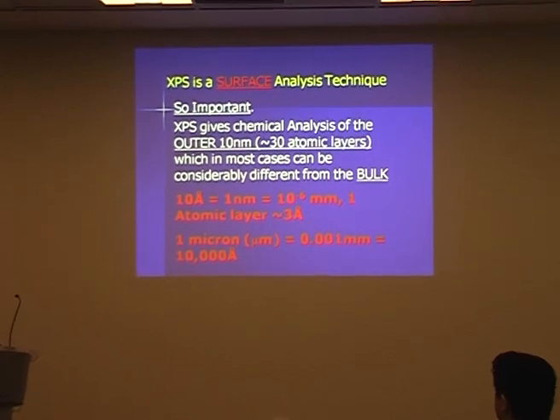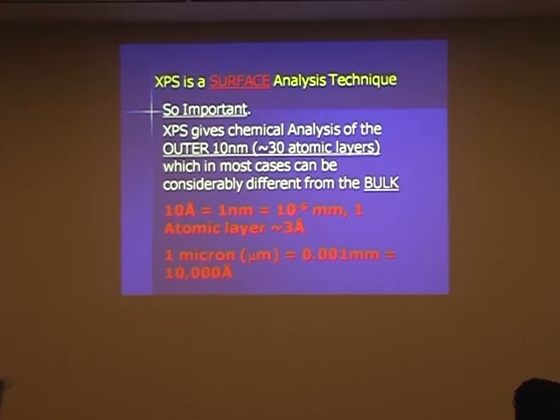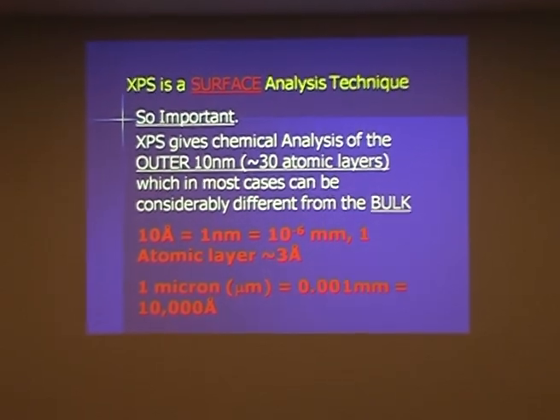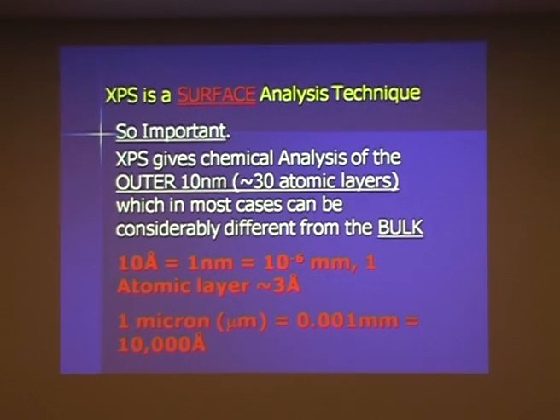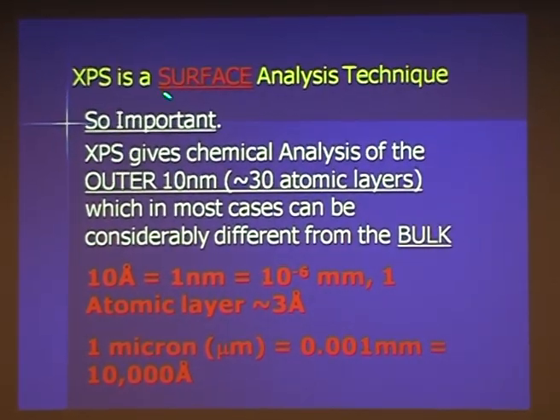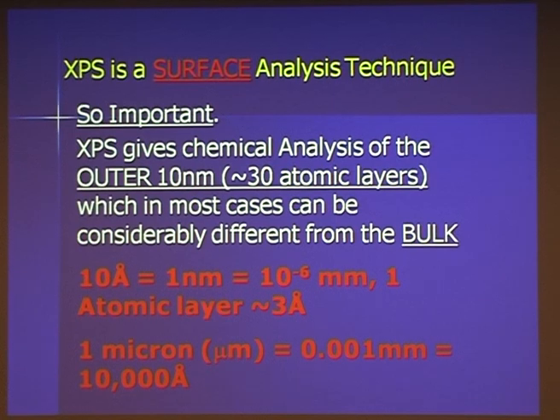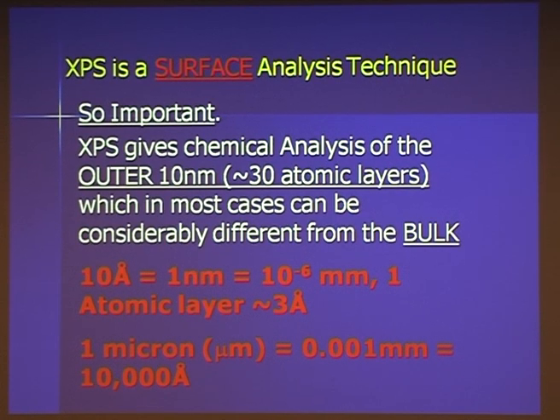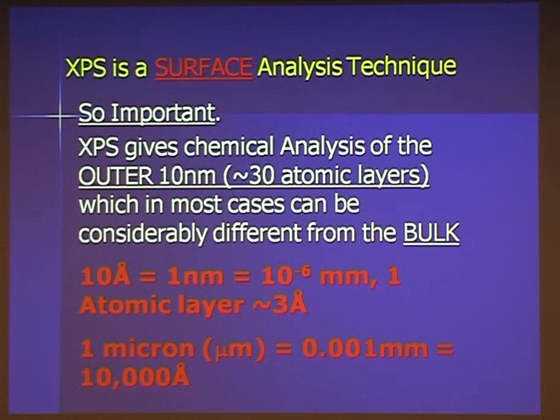XPS is not a bulk analysis technique. If you look in any literature, it's called a surface analysis technique. It gives you chemical analysis very neatly of the top outer 10 nanometers — that's about 30 atomic layers. And it's considerably different most of the time to the bulk, because the sample's been exposed to some solution, been exposed to the air, and some samples are very reactive, so you get a different chemical composition on the outer surface than you do into the bulk.